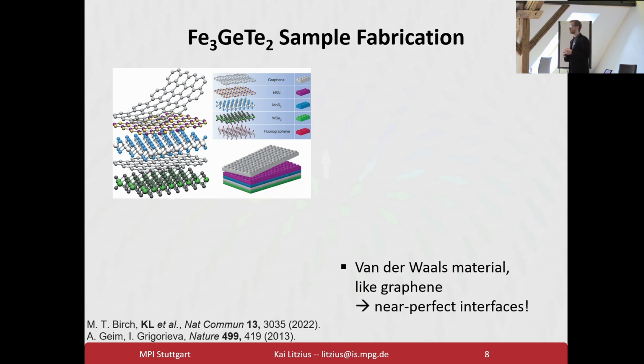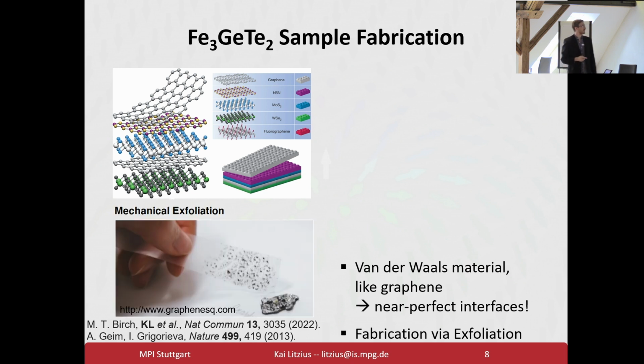And these generate really clean interfaces because you have a monocrystalline material that you exfoliate and just stack together. And the exfoliation process tends to be comparatively easy by ripping off material from a crystal and taking these flakes and creating devices out of them. And at least for experimental tests, this is all totally fine and works out nicely.